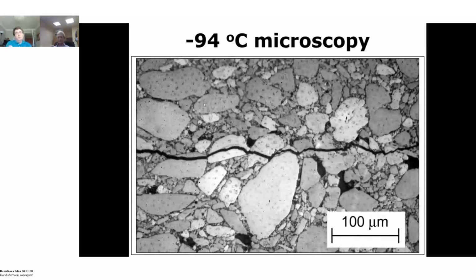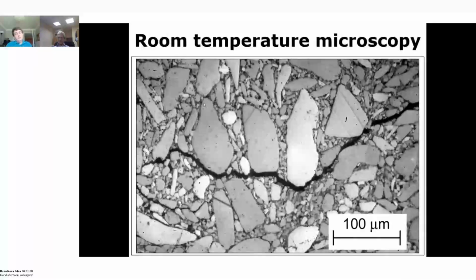material. Now, one of the things that we think will be interesting to follow up on this system, but we did not do it at the time, was to look at those deformation maps and see how much they varied statistically from the perfect homogeneous material and how that changed with temperature. That would be an interesting study, because it would show the effect of the microstructure and the microstructural failure process, this versus that, on a much more global scale in the response of the system.